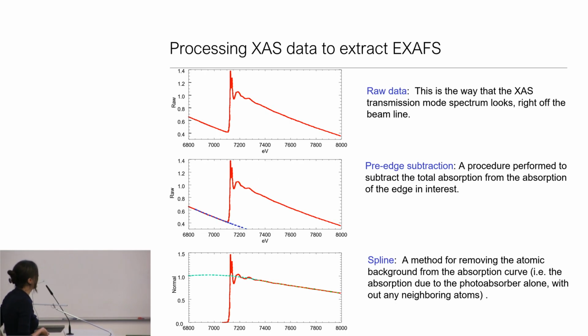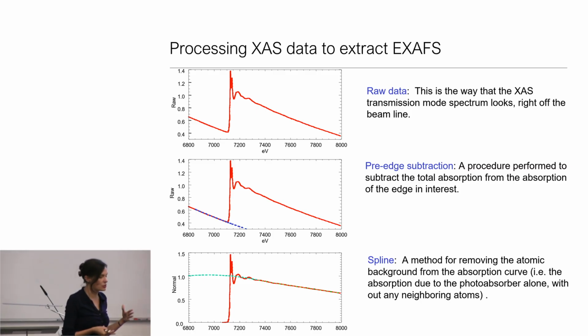Okay, so what does the data look like off the beam? Because obviously, when you're just collecting X-ray absorption spectroscopy, you don't initially see anything that looks like EXAFS. So what we do is we've already measured our raw data in energy space. We typically subtract a background that has to do with any sort of lower energy absorption or scattering events that we remove. And then the next thing we do is to spline our data. And here we're actually trying to remove the atomic background from the absorption curve of interest. And so the spline, in effect, is basically trying to model very low frequency events that would have to do with scattering off the atom's own interatomic potential.